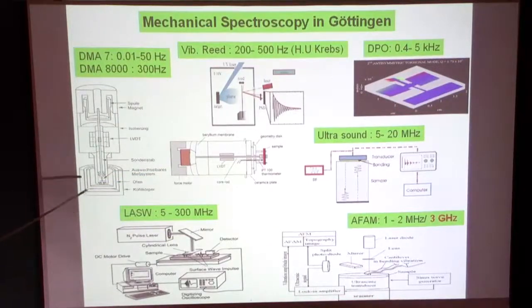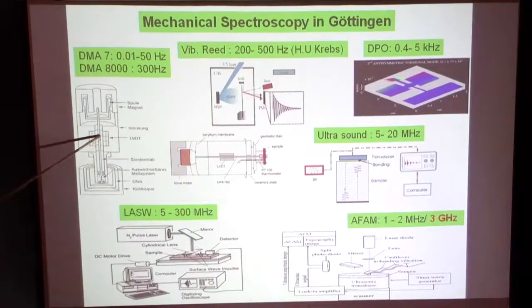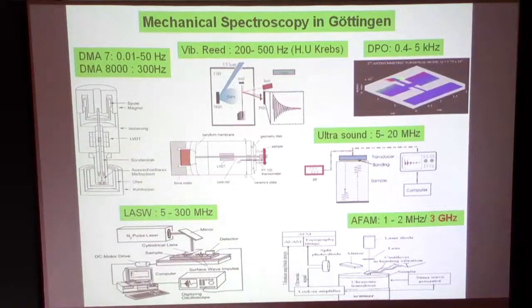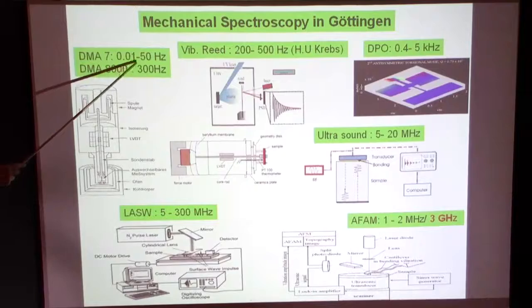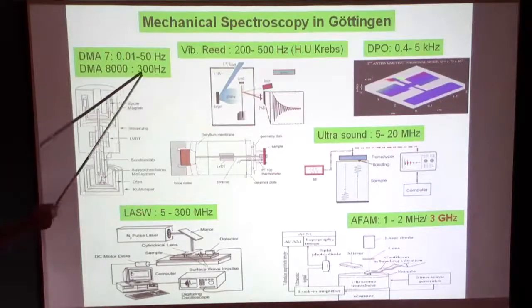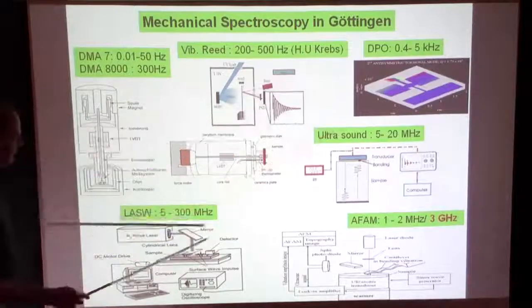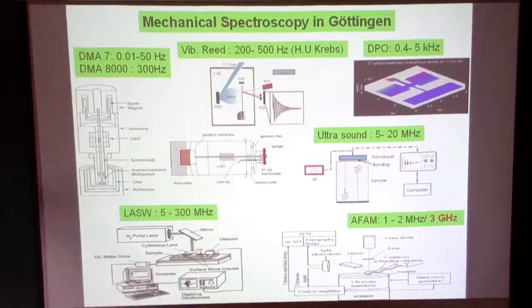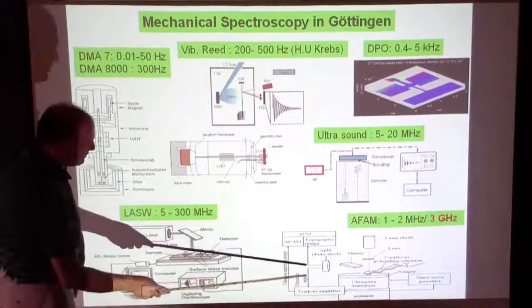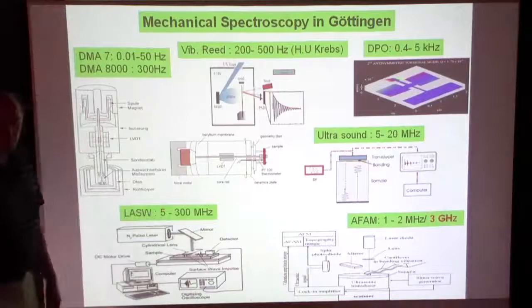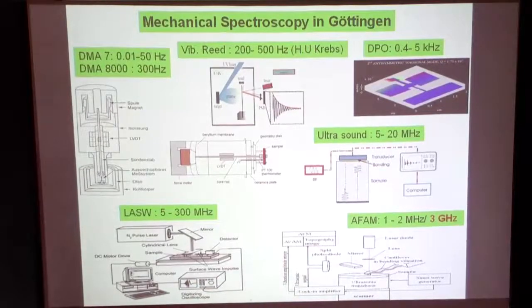The workhorse today is this very simple dynamic mechanical analyzer, which works with a loudspeaker and has a sample down here. In the middle there's a little magnet inside coils, and you pick up with this magnet the amplitude and the phase of the response, and you excite between quasi-static 0.01 hertz to 50 hertz. A newer machine goes up to 300 hertz. Then there are other things I don't want to say. Ultrasound, obviously, 5 to 20 megahertz. Surface acoustic waves, I won't talk about today, but I will talk about the AFM, atomic force microscopy measurements, which locally excite the system, and you can make local modulus measurements.